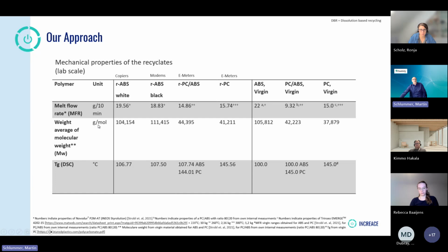We have average molecular weight distributions very similar to virgin, so there's no indication for a specific degradation somehow, despite the fact that we start from a very, very mixed feedstock. It has been totally undefined from the waste that we got. So it is in the end quite funny that the products are still in the same range. And if we look into the DSC, we also have the typical values here, which indicate that our products are really the indicated ABSs and PCs and so on.